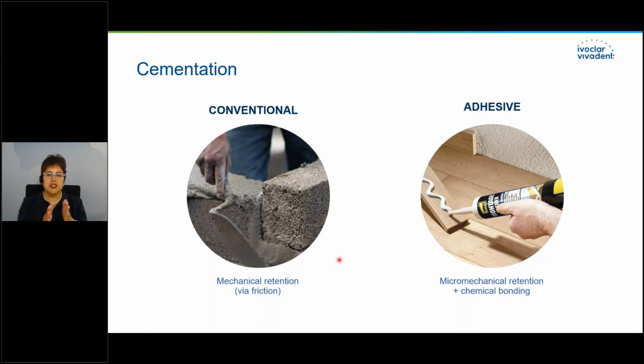So for the conventional cementation, we will have a gap between the tooth and the restoration, and ideally we will have it with parallel preparation so we get a higher friction. So the retention is also influenced by the gap. So less gap, you will get more retention. Another important factor is the roughness of the surface. The main mechanical retention is done via friction. On the other hand, we have the adhesive luting protocol. Additionally to the micromechanical retention, we are using also chemical bond.